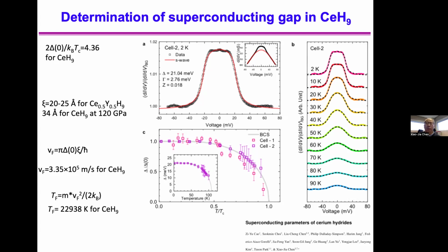We also use point contact spectroscopy. That's from my student Ziyu Cao in collaboration with a group in Korea. You can see we measure from the normal state to the temperature down to 2 Kelvin. Then we have the gap function changing with the temperature. From that, you can determine 2 delta 0 over kBTC. That's pretty low compared with our lanthanum H10. That's a little bit low. Since we determined the upper critical field, the coherence length can be determined. It's also very low, around 20 to 25 angstrom.